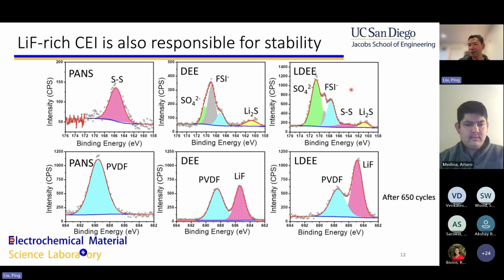And then we also observe a variety of sulfur species on the surface. Without going into too much detail about exactly the reaction mechanism, I want to tell you that what this particular electrolyte does is form a protective layer on the cathode surface that isolates the sulfurized PAN material from the electrolyte. It doesn't really work in a diluted ether electrolyte.